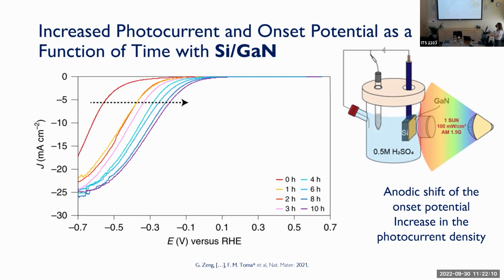So we tested the material at time 0, and then we started running chronoamperometry, which is our way to look at stability of material over time. And then we took cyclic voltammograms, or linear sweep voltammograms in this case, every so often to just try to understand if the material was changing, and it was. And surprisingly, it was improving, which is kind of unexpected. And so we tried to understand why the material was improving.